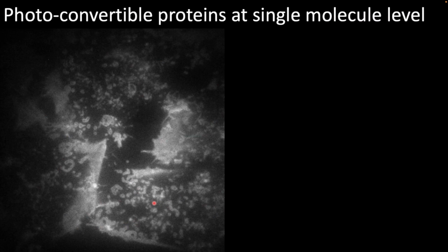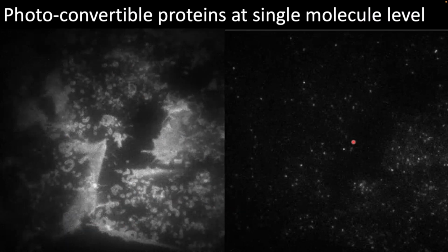The mEos protein is photoconvertible, which means that it is originally in a green state and it's expressed everywhere. So if you just look at the green channel, you see a diffraction limited distribution of this protein. But if you look at the red channel, and if you put a little bit of UV light, you'll see an image like this, just a few dots. Every one of these dots is a fluorescent protein that is in the red state. The reason why these look so different is that in the case of the dots, you only have a small subset of the proteins in this red state.